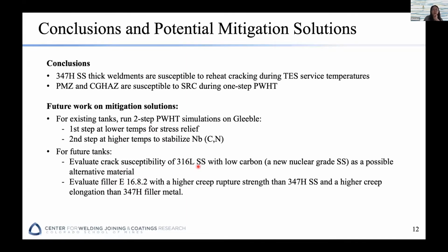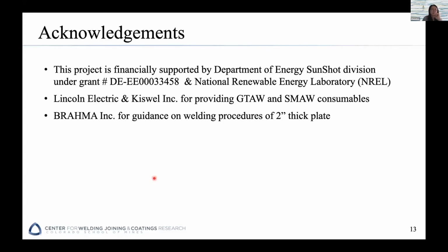And for future tanks, we would evaluate other materials instead of 347 stainless steel. We will try 316L. This is a new grade that has extremely low carbon concentration that was originally developed for nuclear applications. So we think this might have less crack susceptibility. And we will also recommend replacing the filler from the original 347H filler to the E16.8.2 filler that has a lower susceptibility as well.